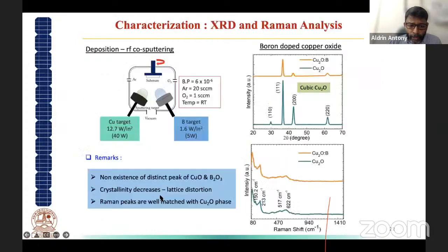And this is how we did the fabrication of the solar cell. So how did we prepare this material? The copper oxide was formed using a sputtering method, and boron doping was also performed, using a co-sputtering method with copper and boron targets in the presence of oxygen and argon. Argon was used as the sputtering gas, and oxygen as a reactive gas for sputtering.